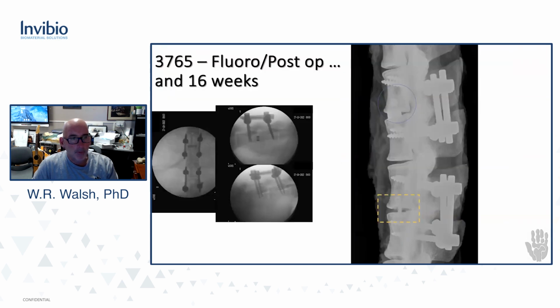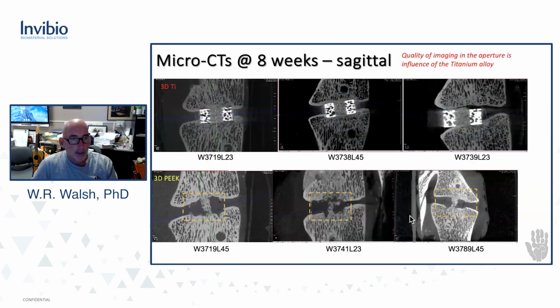And I'll just cut to 16 weeks, same type of analysis where we look at our post-op fluoros for the positioning, make sure there's no problems. And again, with the titanium, we really can't see what's happening inside. The interface looks like it doesn't have a fibrous tissue interface. The PEEK, we can see that there's actually an aperture, and we can see bone going from one vertebral body to the next. And then we look at micro CT.